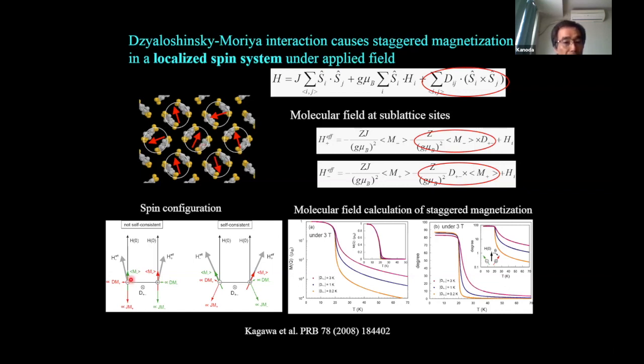Okay, if you apply a magnetic field in this direction, upward, in the paramagnetic state, usually the magnetization should be aligned along this line, the green curve and green arrow, red arrow. However, if the DM vector is perpendicular to the screen, in that case, this spin and the DM vector give a perpendicular field at the neighboring site. This is due to this DM term. So this spin should align, and the same situation occurs here. So self-consistently, finally the local spins should incline against the applied field.